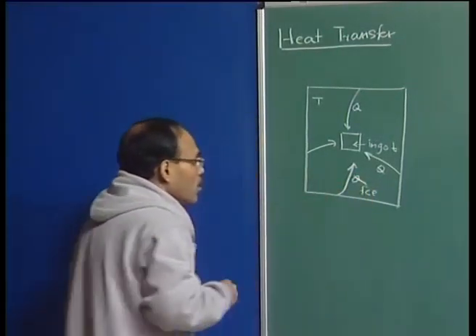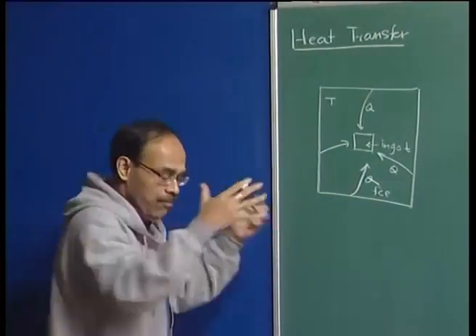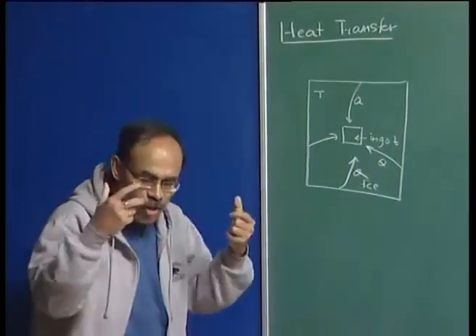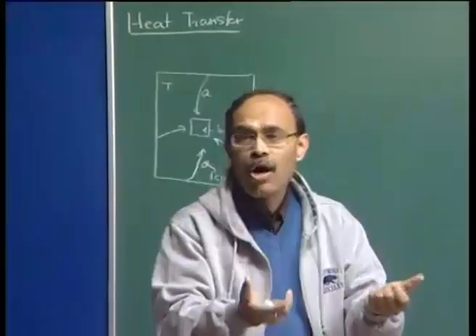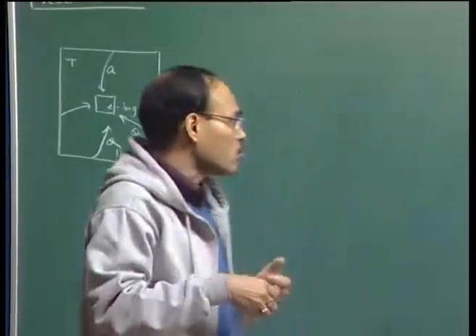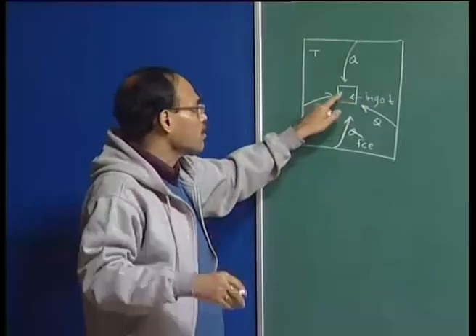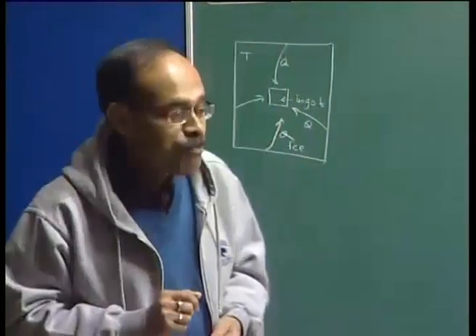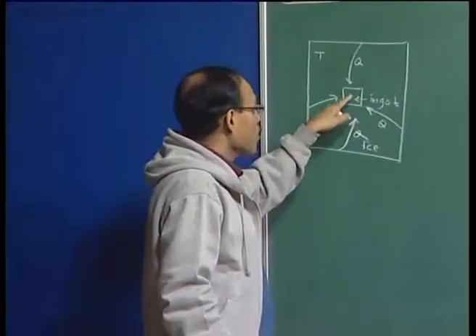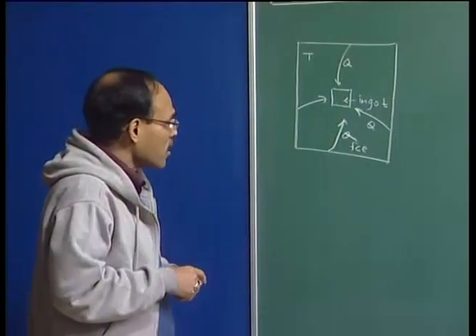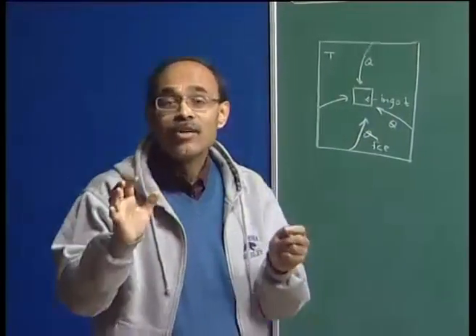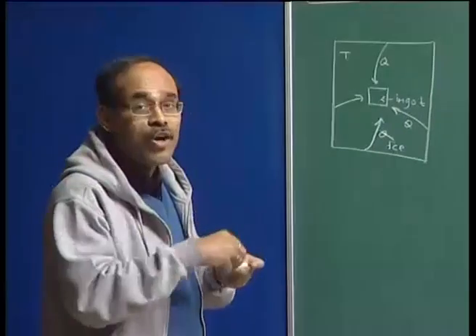If you want to predict the homogenization time — suppose I have an ingot placed within a furnace and I want to find out at what time the ingot has become completely homogeneous — I will only then take out the ingot and subject it to rolling. Prediction of complete homogenization time, or a uniform rolling temperature in the heating furnace, is of key interest. Unless we know the fundamentals of heat flow within the furnace, from the furnace environment to the solid surface and then within the solid, we cannot calculate the optimum reheating time.